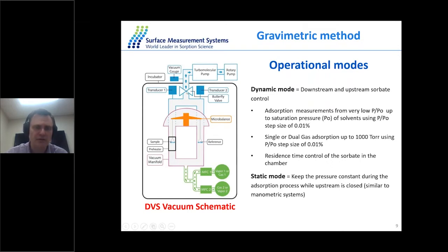So we have two baratrons to measure absolute pressure of vapors, gases, organic molecules. We have another high pressure gauge for measuring high vacuum, so that the turbo molecular pump is fused. And on the sample side, we measure the temperature with the preheater. So this is what I describe as the dynamic mode. The benefit of dynamic mode is that we can go to extremely low partial pressures, to the ppm level. So the lowest pressure we can control and measure is 5 millitorr. Okay, and then you have to recalculate how much it is in the P over P naught or ppm level.